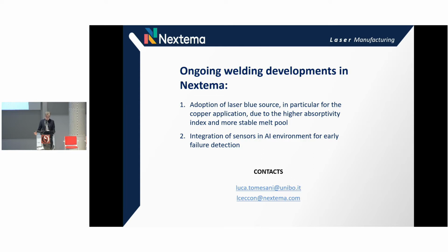This is a very last sketch about what Nextema is doing in this field. They are adopting a laser blue source, in particular for copper application, of course, due to a higher absorptivity index and more stable melt pool. And they're also integrating sensors in artificial intelligence environment for early failure detection. So, thank you very much.